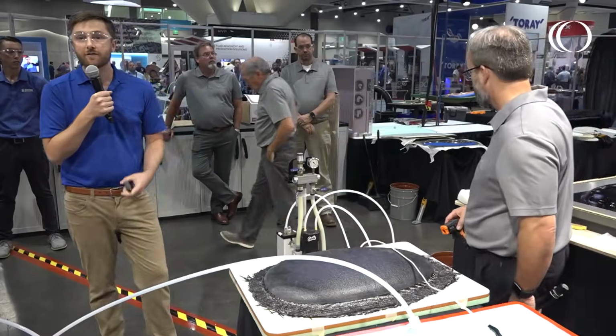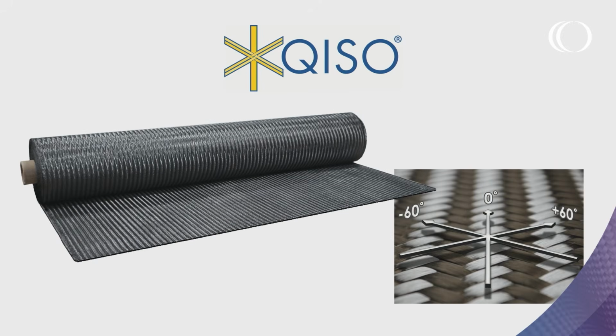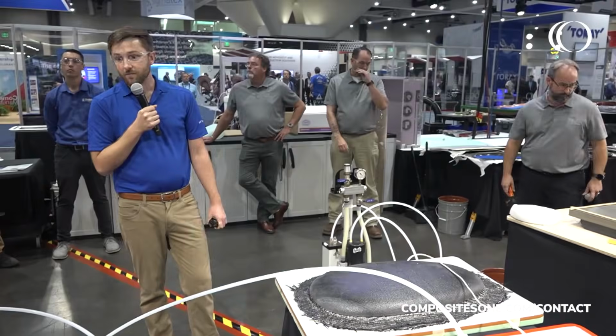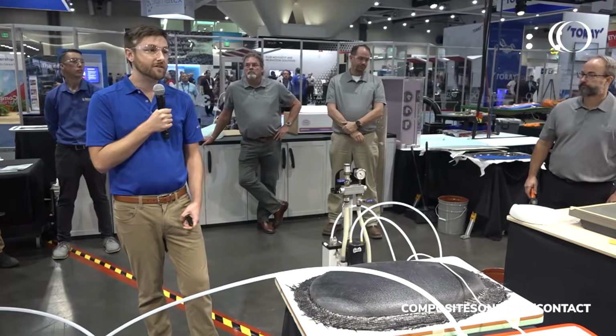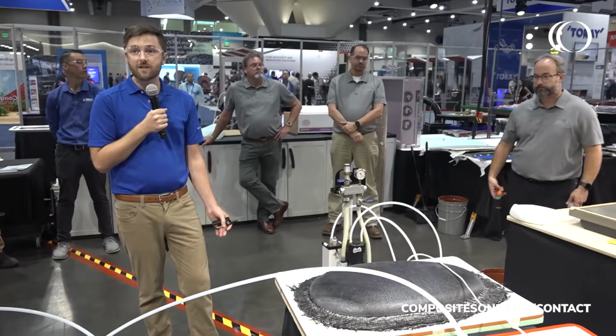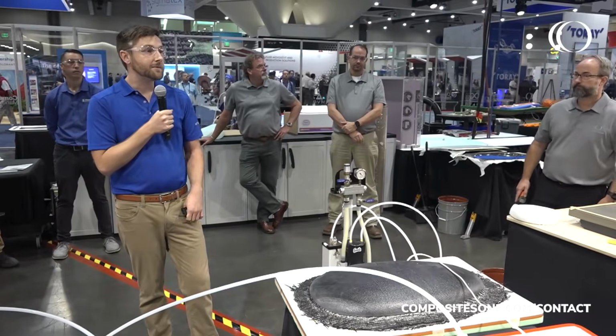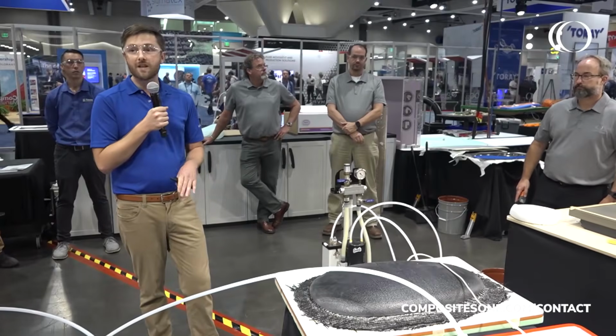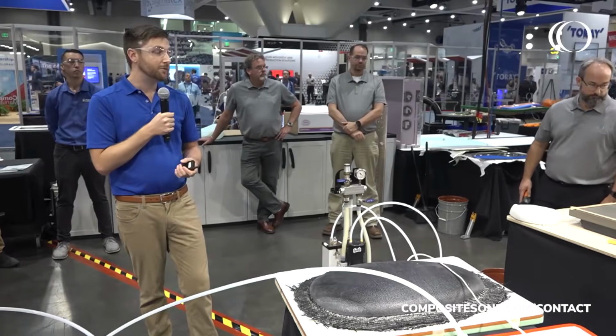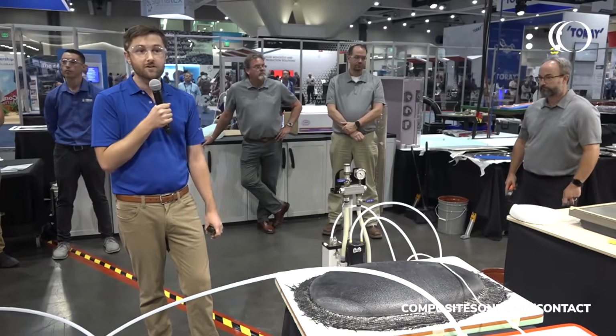The Qiso material itself is a really unique material. As I said before, it is quasi-isotropic in plane, but it is also balanced and symmetric in a single ply. So what that means is you can actually cure single ply laminates out of Qiso that don't warp or potato chip, which is great to keep dimensional stability of your part. It's also a multi-axial material that is still highly drapable, and that's because it is not stitched together. It is braided, so that means that the individual tows are still able to slide past each other, which means it's highly drapable and conformable, as we're showing here today, to this dome shape.